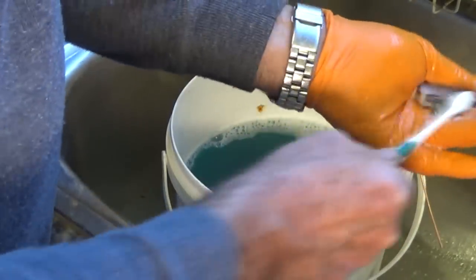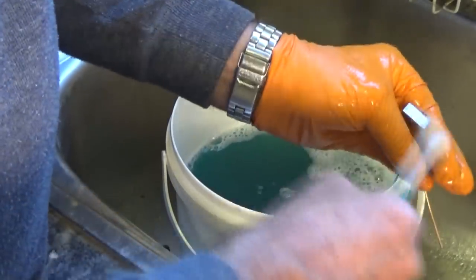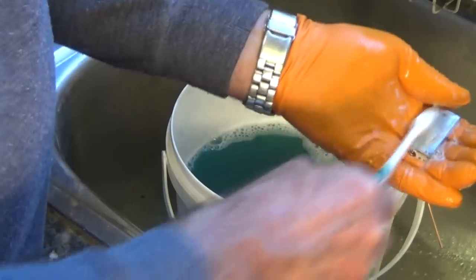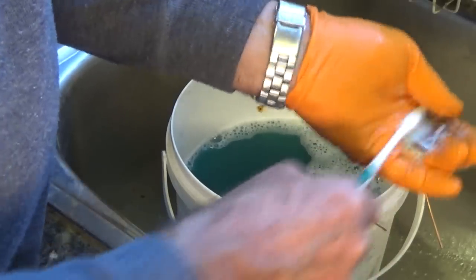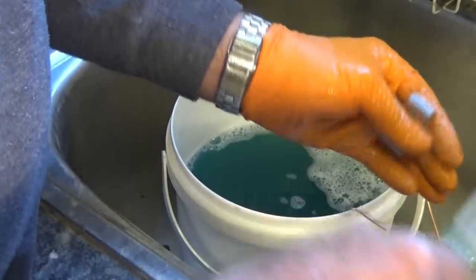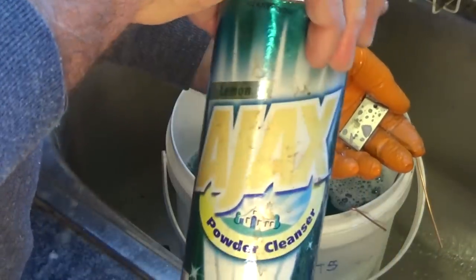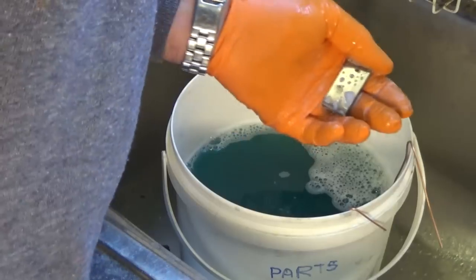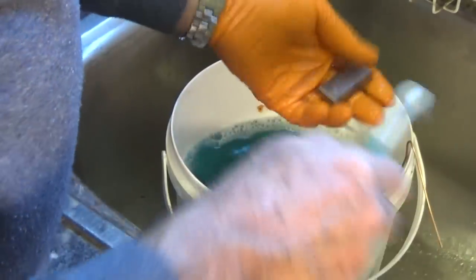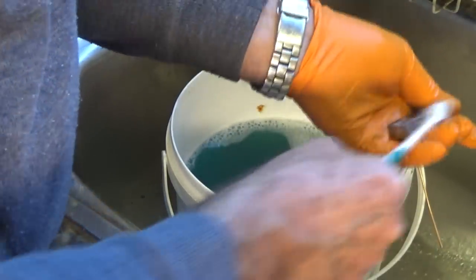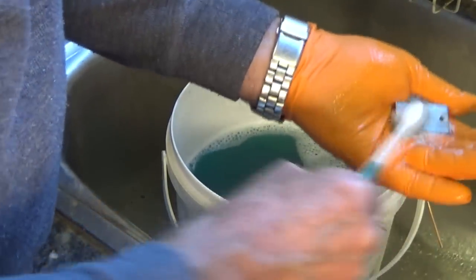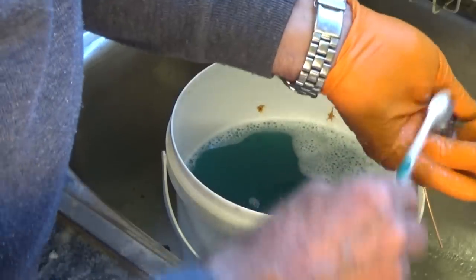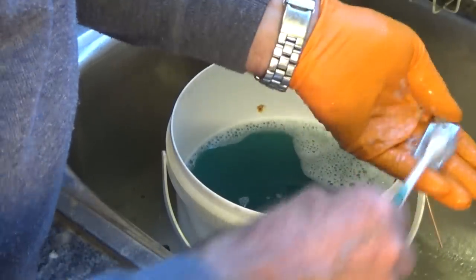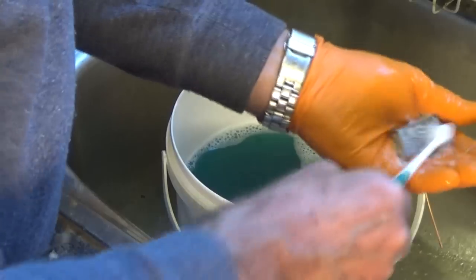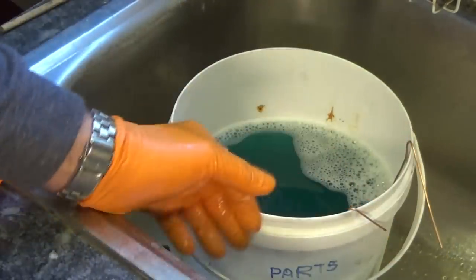I find that this parts wash works pretty well, but if you do have a part that's particularly troublesome, you can't seem to get rid of that waxy or oily film, I find that just using this stuff, just the ordinary old Ajax, seems to do the trick. There's something in the Ajax that chemically cleans the steel, and also I think it's because it's a little bit abrasive that works really well. You still go back into the parts wash to finish and then water rinse. Okay, I'll get them all done, then we'll parkerise the lot.